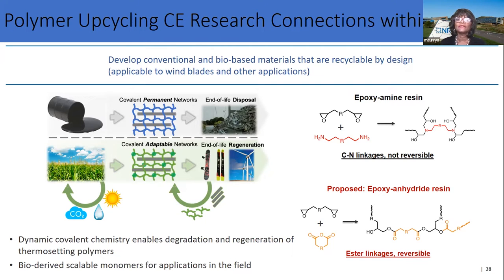And so some of the epoxy amines that are currently used, NREL has researched to produce bio-based anhydrides that are used as part of the epoxy linkage, the epoxy anhydride linkage that ultimately can be reversed. And so we can break down the components into their monomeric precursors and then reuse them at the end of life. That is the concept, and we're well on our way to realizing this. Next slide, please.